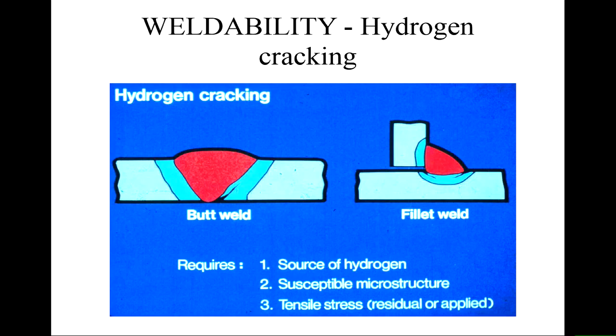So hydrogen cracking is the biggest problem, probably, with field welding. It tends to occur in the heat-affected zones. As you can see here, the light blue areas are the heat-affected zones. The crack might start at the weld metal. It tends to start at the toe of the weld. So this is the fillet weld of the toe, right at the edge. And the crack you can see running in there, and it's running underneath.